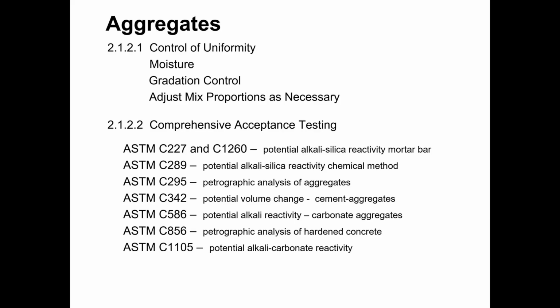But for bridge and commercial products, each aggregate that is in use should have a gradation test conducted at least once per week. If it's an architectural aggregate, like a face mix aggregate, that the volume of the aggregate that is used is pretty limited, then the requirement is that a gradation test be done once every 2 weeks. All right, so that's gradation testing requirements.